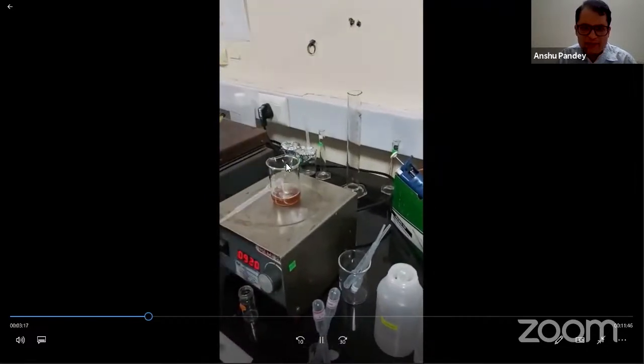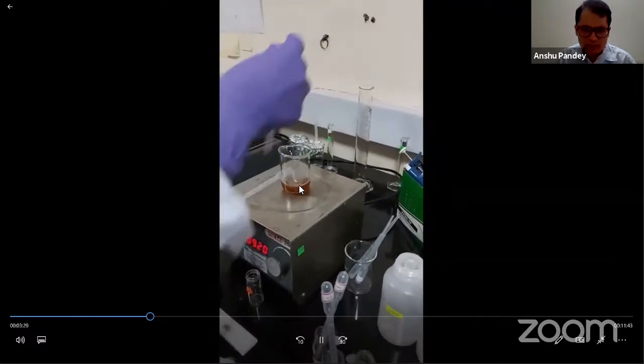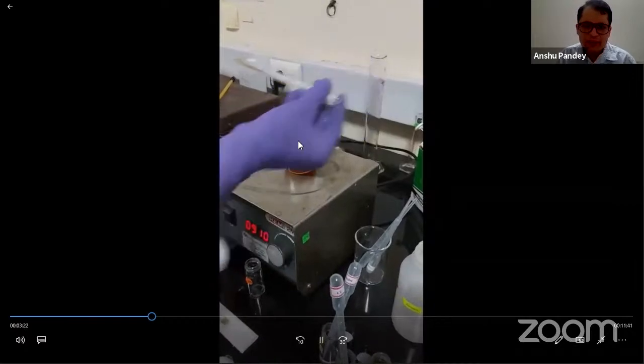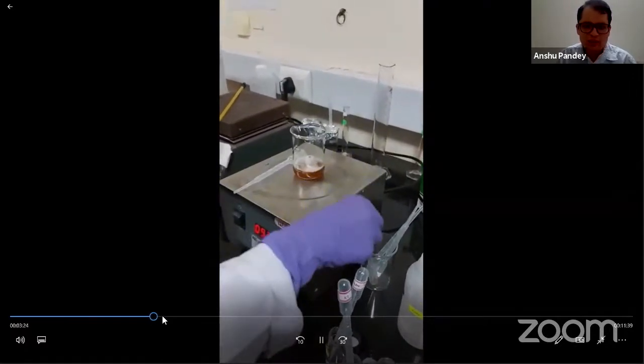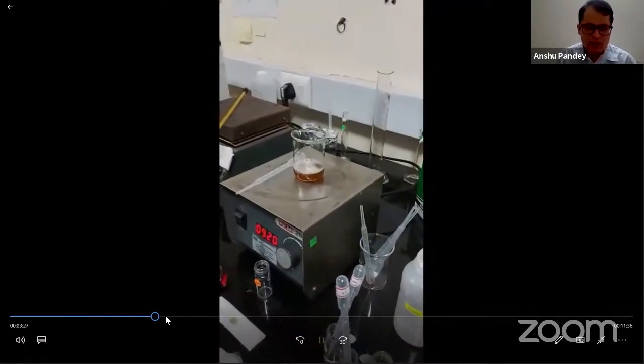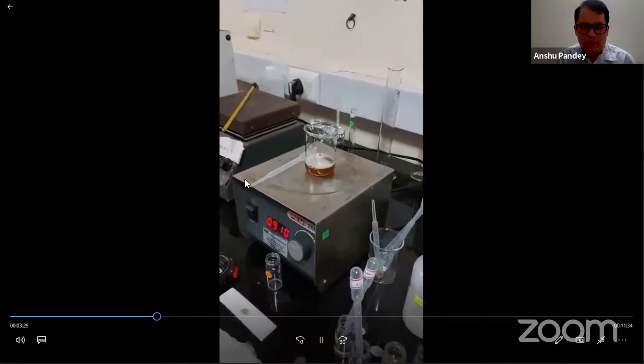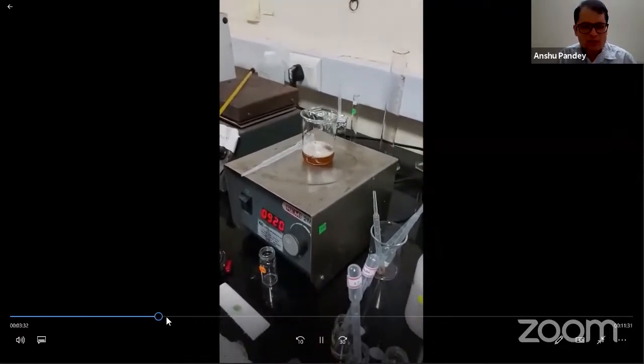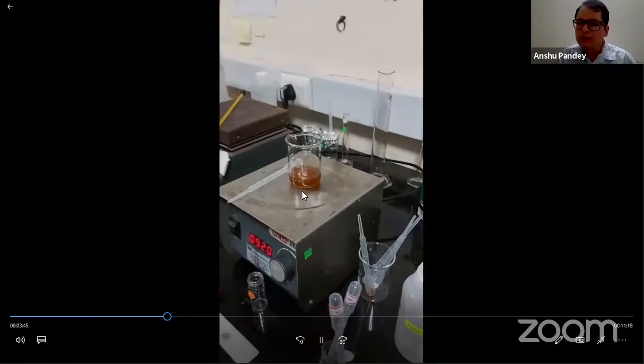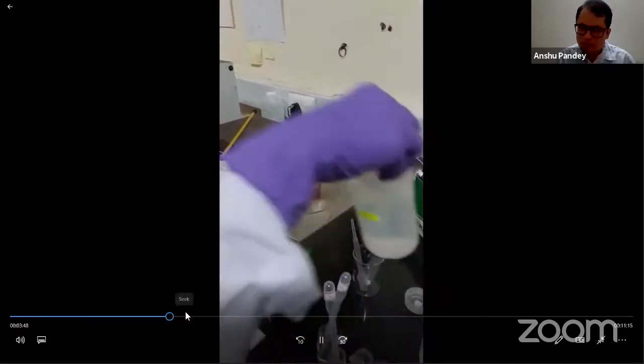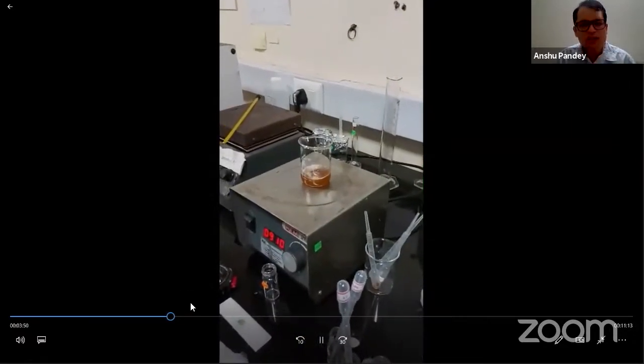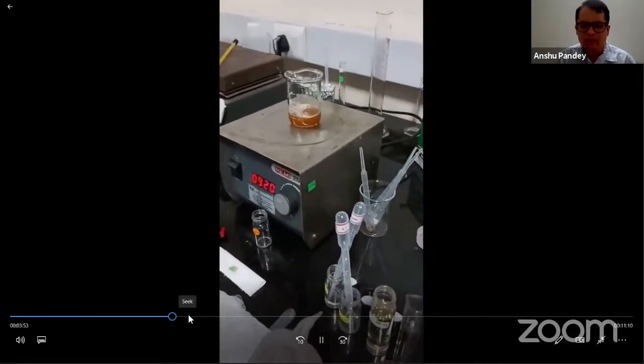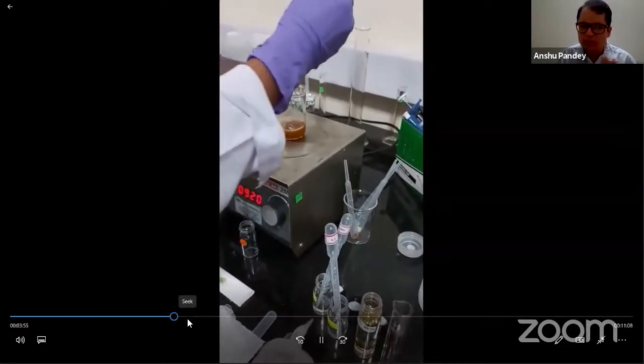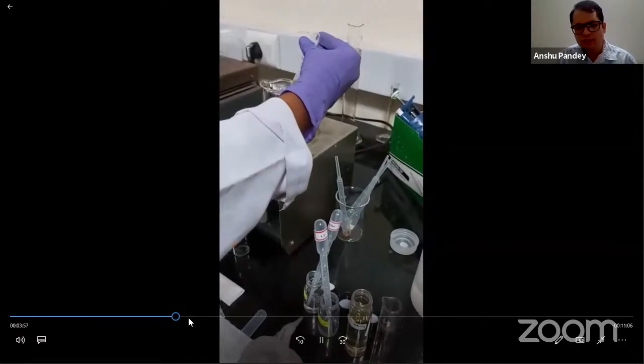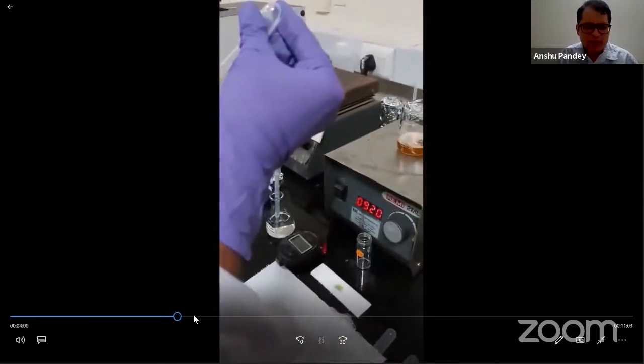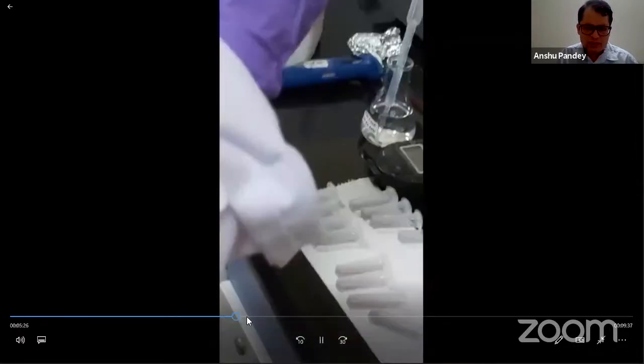But that's about all. At this stage, borohydride was added using one of the vials and the other one was cold solution. Initial spectrum at this stage can be taken. So she has kept an aliquot aside. Subsequently, what is added is the propanol. So as soon as the propanol is added, then it becomes rather critical how fast you handle the material. So far you can see that it's being done in air. All these steps so far don't really worry with air at all. Air does not have an effect because we are dealing with regular gold and silver chemistry. So at this point, it's loaded into a centrifuge,